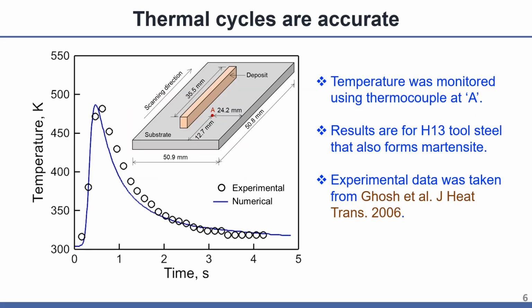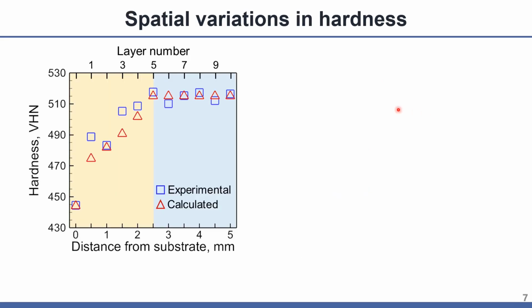The computed thermal cycles were rigorously tested using independent experimental data. The good agreement between the computed and experimental results provides us the confidence to use the computed thermal cycles for evaluating the tempering kinetics and the hardness variations. Computed hardness variation along the deposit height for a 10-layer high thin wall agrees well with the corresponding experimental results.